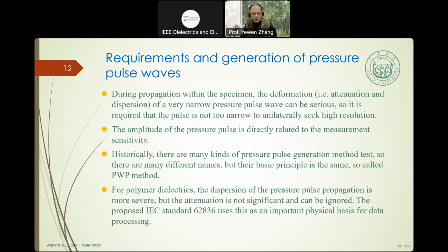In principle, during the propagation with the specimen, a very narrow pressure wave deforms very seriously. So it requires the pulse not too narrow, and not only seeking high resolution. If it is very narrow, the resolution is high, but the deformation is very quick. And the amplitude of the pressure directly determines the measurement sensitivity. So it also needs a suitable amplitude of the pressure. Now we know about 1 megapascal maybe is suitable.